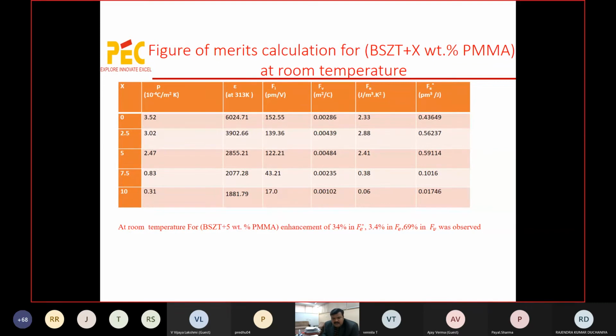But from these parameters, you will not be able to judge why it is better, because we have to go in depth with the different formulas and relations. But somehow in this she has mentioned that x is equal to 5% is the best one for these pyroelectric measurements, pyroelectric character basically. So it means what? It means that x is equal to 10% has the maximum porosity, 5% is in between, and 0% has no porosity. So beyond a limit of porosity, you will not get the good properties. So you have to optimize the porosity, that it should be nearly 5%, not very much more than 5% and not very much less than 5%. So you have to optimize the synthesis by characterizing the materials.